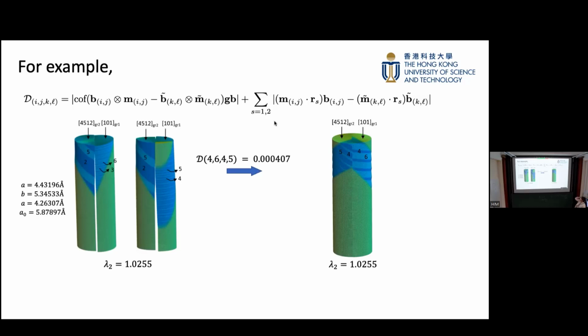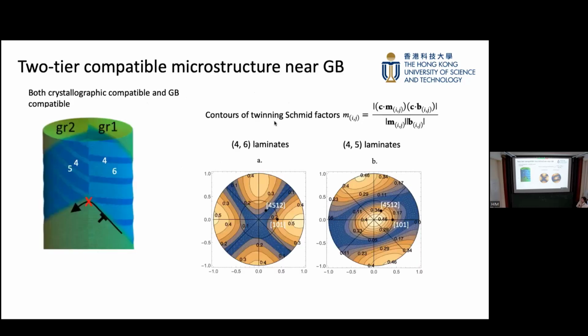And here I want to give some comparison between values of the crystallographic compatibility and this kind of, I call it two-tier compatibility. Since this is the area jump, I just put a square here. As you can see, they're more or less at the same level. That means here you have some elastic transition layer, due to the value not being equal to 1. And here you have some twin laminates that form to accommodate each other at the grain boundary, giving this kind of very small misfit. And how about the shear?